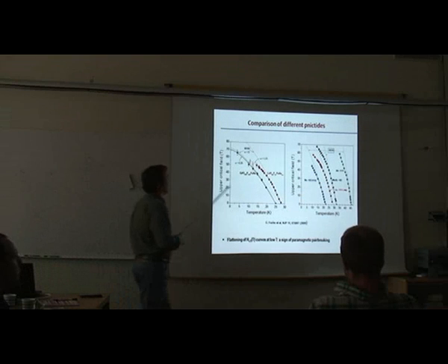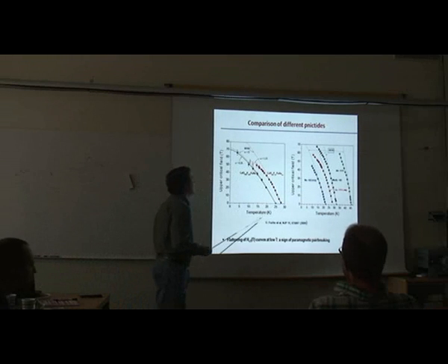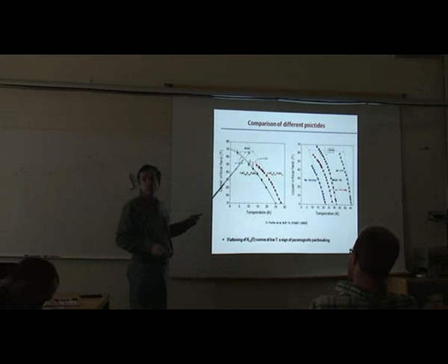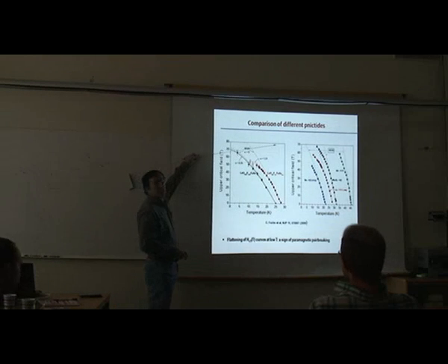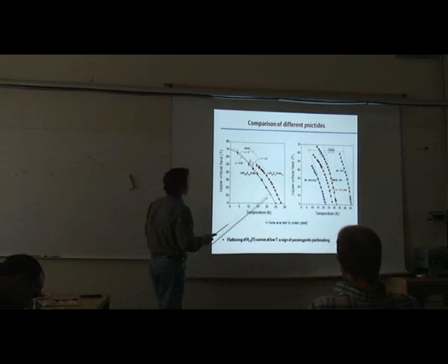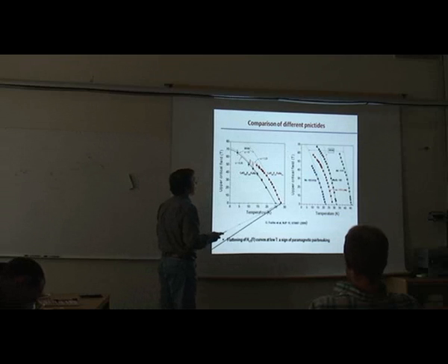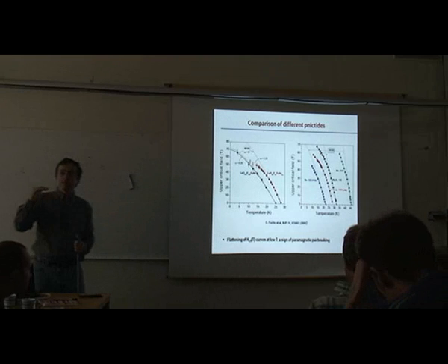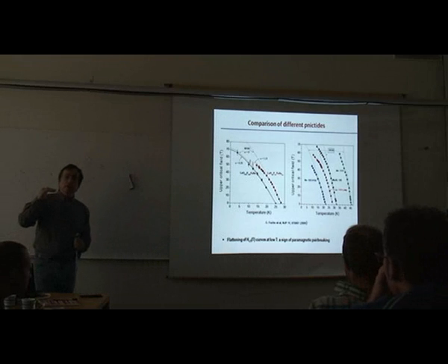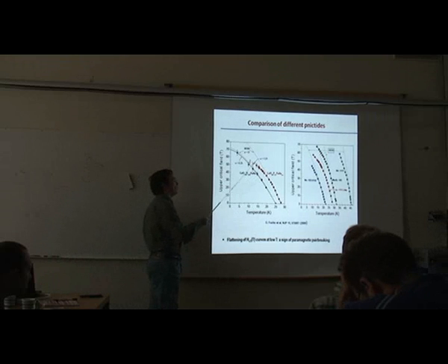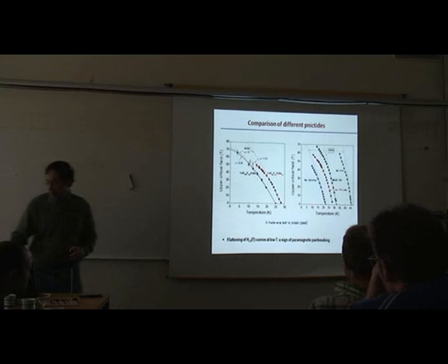However, people did measurements, and we did too, on pnictides which have smaller critical temperatures, and then we have enough data points, because we can actually go to 70 Tesla and measure Hc2. And what you see is it starts linearly here, and then it starts flattening. And this flattening is the first indication that paramagnetic effects come into play. So it's not just orbitally limited Hc2 like here, but at low temperatures, paramagnetic effects become important.